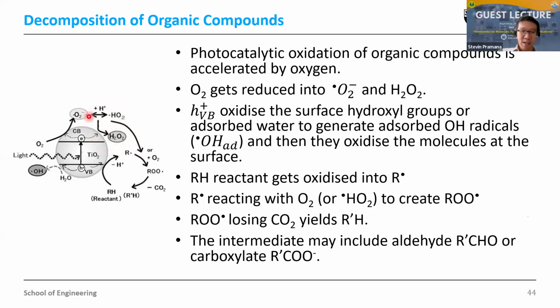So let's keep this first. Then what happens on the hole side? The valence band hole plus, as we discussed before, can oxidize either the adsorbed water H2O or the surface hydroxyl, and it will create the OH radical, so OH adsorbed here. Then this can oxidize the molecules at the surface. This OH or this H plus can react with the reactant RH. For example, if you assume R is an alkyl group with hydrogen, it will create the R radical, R dot, by losing the H plus, and this R dot will react with the radical coming from the chemical reduced by the electron.